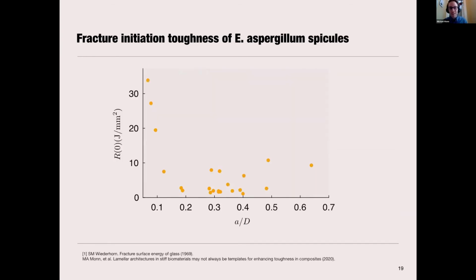So here we can see the initiation toughness, again, as a function of A by D. And this increases as your A by D becomes very, very small, less than 0.1. But in a middle range of A by D from, let's say, 0.2 up to 0.7, it's relatively constant with a value between 1 and 10 joules per millimeter squared. Again, human-made glass is shown to have initiation toughness around 7 joules per millimeter squared.